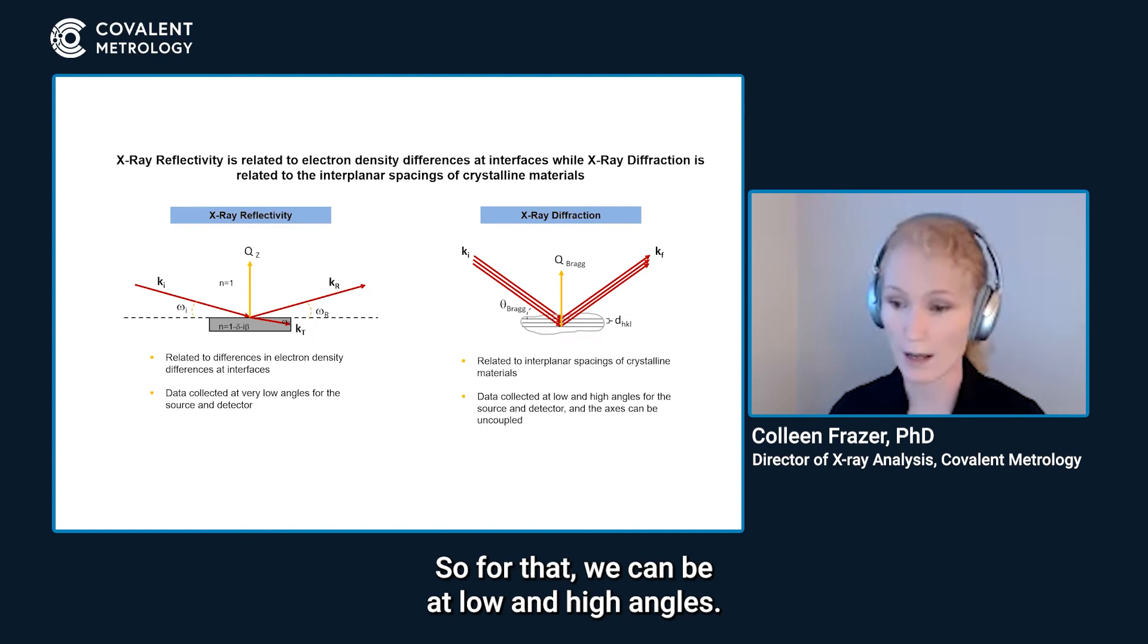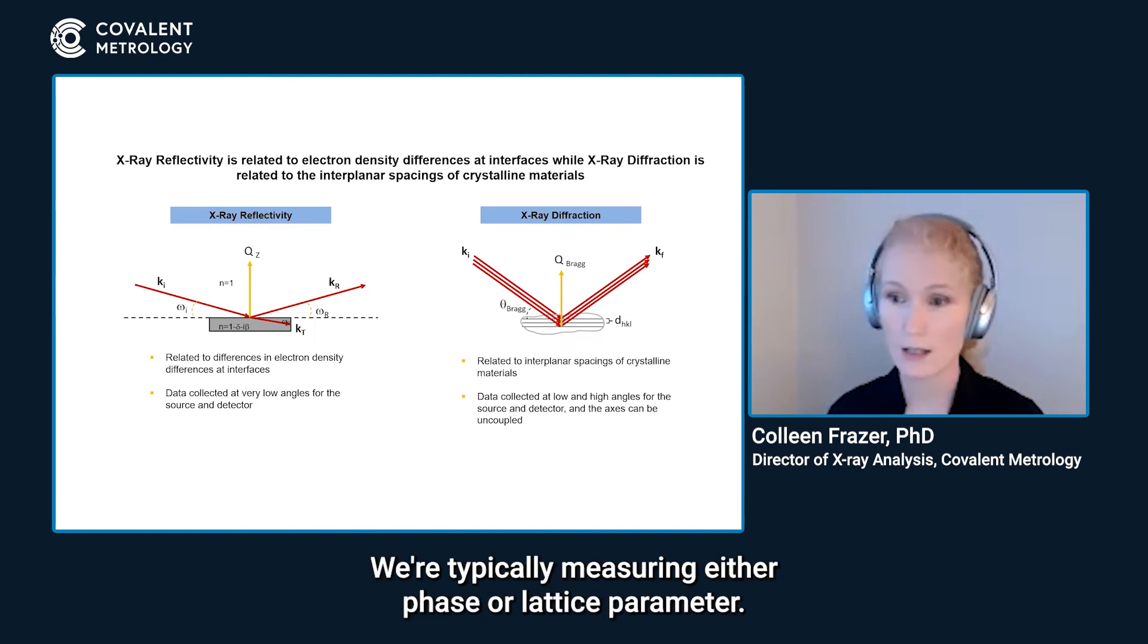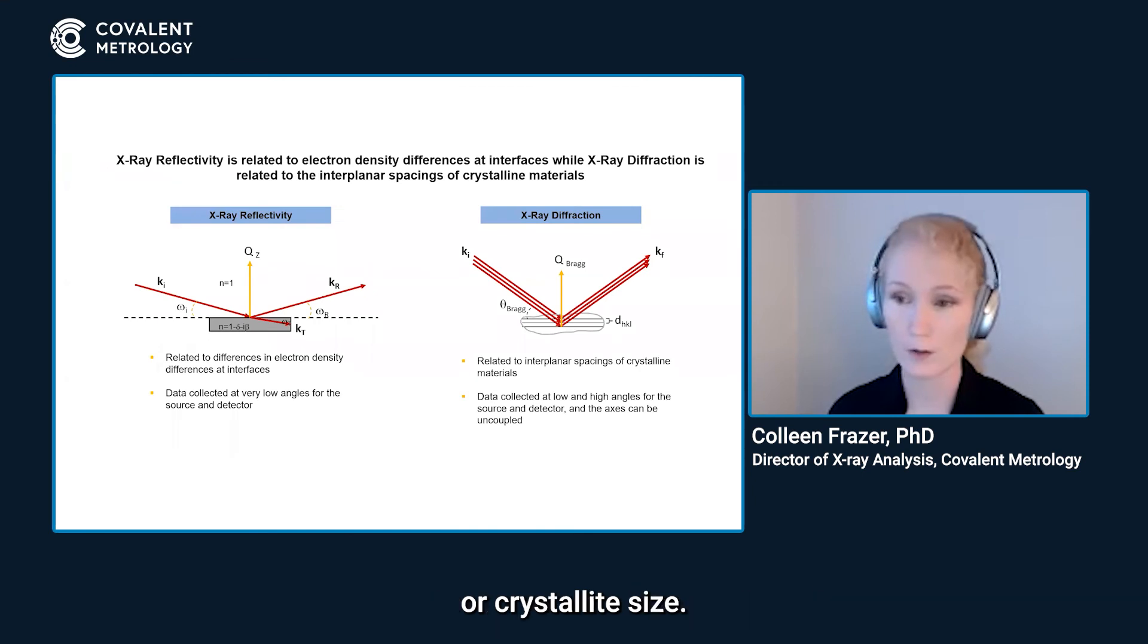So for that we can be at low and high angles. We're typically measuring either phase or lattice parameter. Sometimes we can calculate crystallinity or crystalline size. Those are more along the lines of what we do with diffraction.